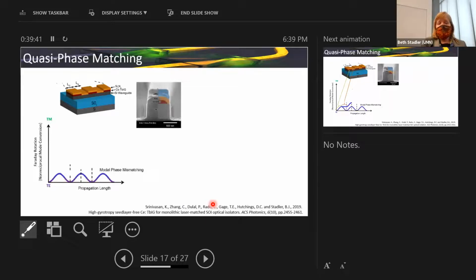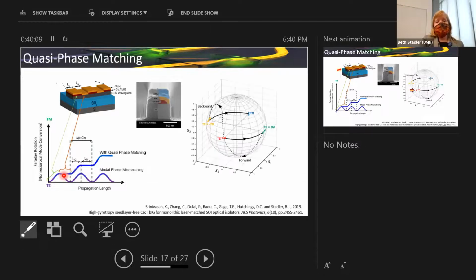Here's what the mode wants to do. Never quite getting to TM, maybe not even going more than what we call 1 degree of Faraday rotation. But if you can stop the cladding from being magneto-optic, it will actually rotate and then not rotate. And when you get back to the place where the beat length is starting at 0 again, it'll rotate again at that point. And you can just build up your cladding to give you rotation by canceling rotation every half beat length. Turns out you can also, and this is just kind of the Stokes, I'm not going to go through this, but it's how it works on a Stokes sphere.